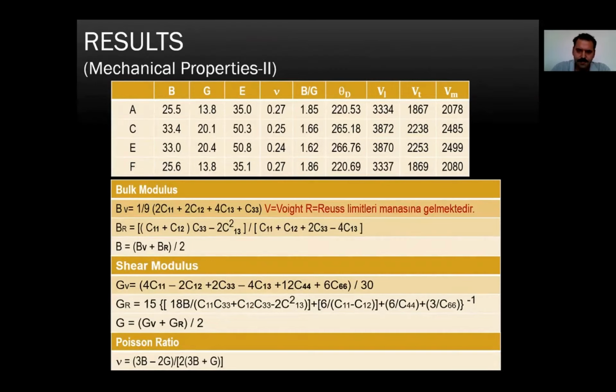As can be seen, the B/G value is greater than 1.72 for A and F, so they show ductile properties. It is less than 1.72 for C and E, which means that these models are brittle. This result is important in terms of showing that the physical characteristics of different slices of the same material may be different.